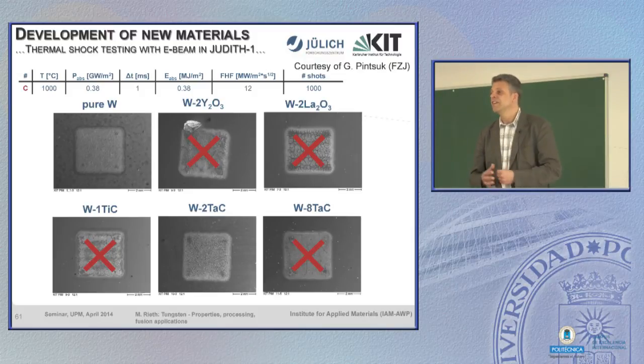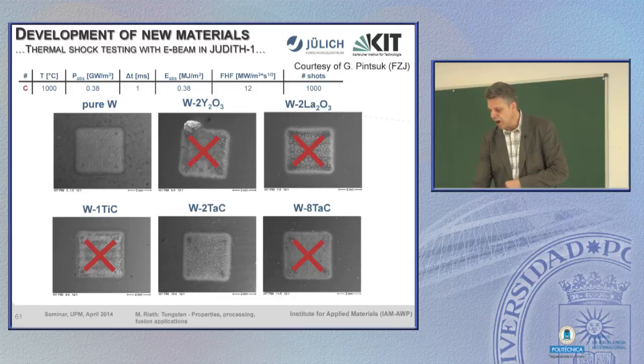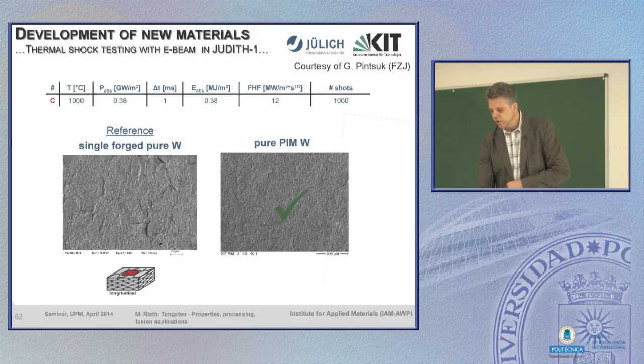So with this type of test, we qualify the material for their armour behavior. Again, we did this same test. This is 1,000 shots. This is a commercially fabricated plate. We see cracks on the surface of the testing, and with this pure powder injection molded tungsten, you don't see. So there seem to be some benefits for this material.